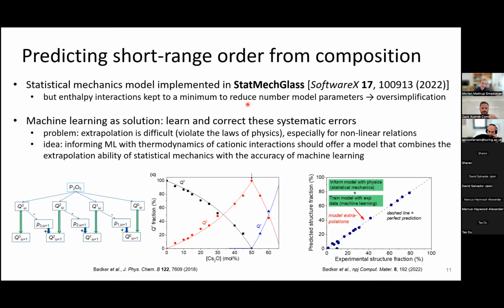So then, of course, it's always the dilemma: do you include all the data to get a bigger data set, or do you choose those where you are more certain about the compositions, because the nominal and the actual ones can vary a lot. In the experimental data, like in the study I've shown here, this was trained on 400-500 glass compositions. When we put these restrictions on them, we are in the hundreds, of course, at the limits of where it even makes sense to use neural networks, right? But when we go to training on the simulations, that is a different story, because then we have thousands and thousands of data points. But yeah, I would say curating the data is a key issue in our field.